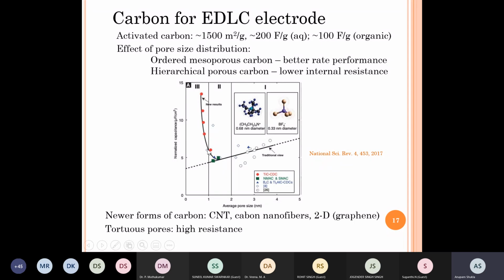One of the ways to explain it is that at very low pore size, the hydration layer goes away. There is a solvent molecule layer around each ion in a solution, and that layer goes away. Therefore, the ion size becomes smaller and it can enter the pore. When that happens, you get a sharp increase in the capacitance. This is just to explain that there are a lot of other unexplored things which still exist. Although it's a pretty mature area, there are still possibilities of improvement in the performance of carbon-based EDLC electrodes.